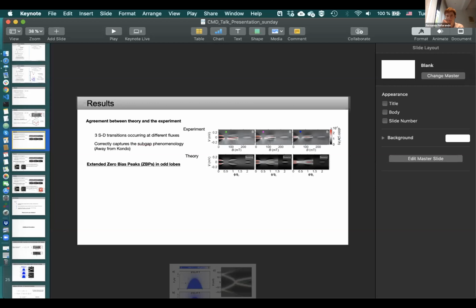Yeah. But essentially, the condition to have the zero bias peak at the first lobe is only the size of the gap, no? Essentially, compared to. Well, essentially, you also have to tune the position of the dot levels, the dot's energy, in order to have these Andreev bound states starting at the appropriate energy at zero flux, so they can develop this extended zero bias peak.